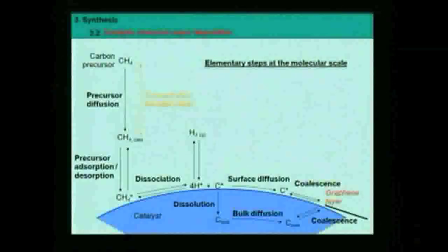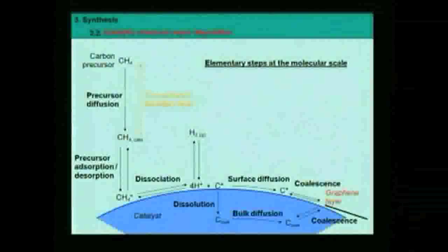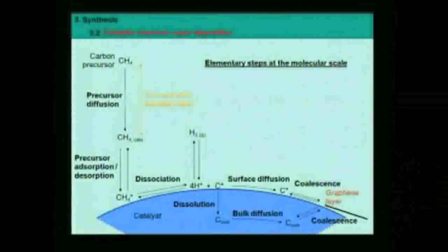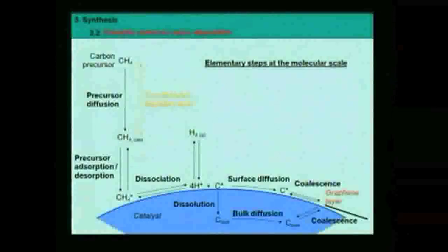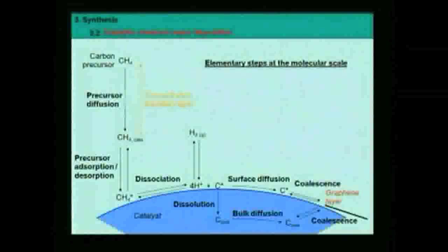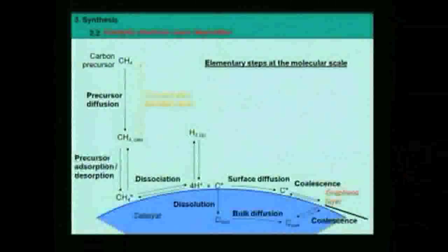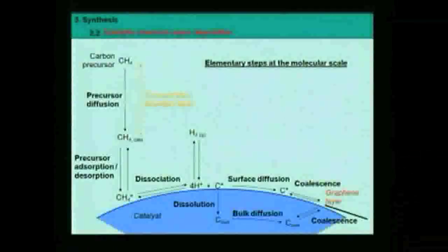Then, because we use a catalyst which is good for assisting dissociation of carbon-bearing molecules, we can have this dissociation and completely, fully dissociate the carbon-bearing molecules into carbon and other species like hydrogen. Hydrogen usually desorbs after forming H2 molecules. Then, to make a carbon structure with several carbon atoms, you need those atoms to meet. So you need them to move, to migrate inside or on the surface of the catalyst. So there are two types of diffusion that can be considered.